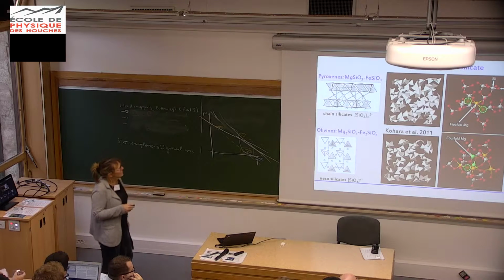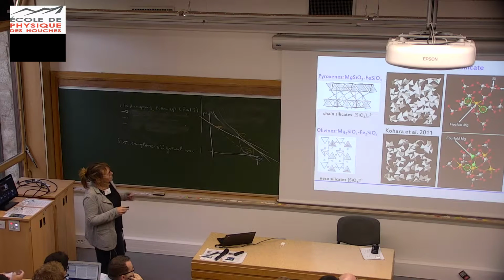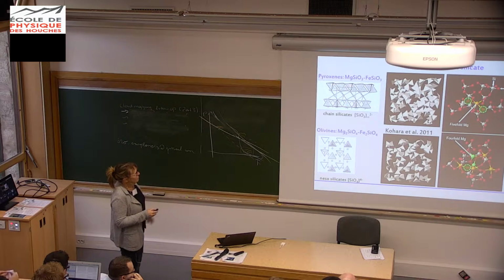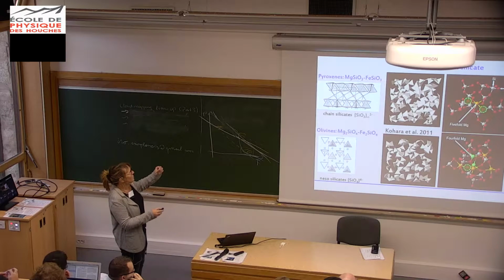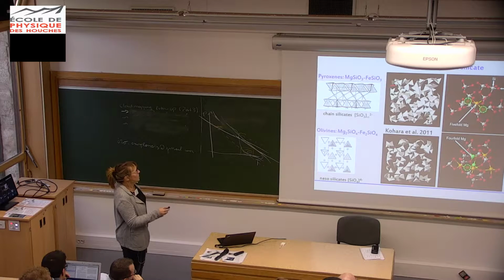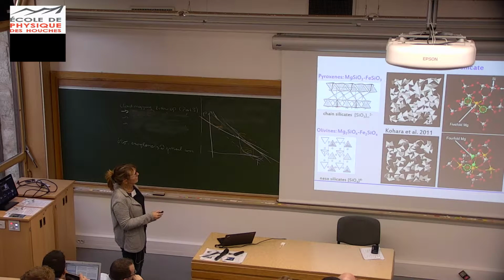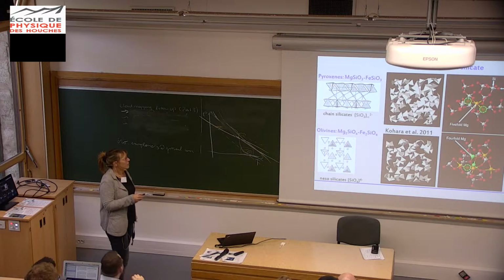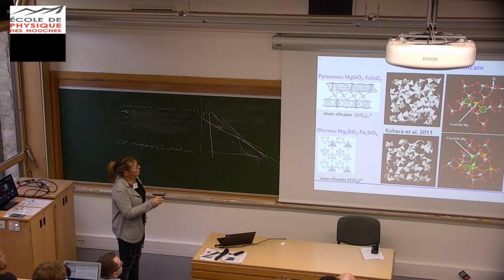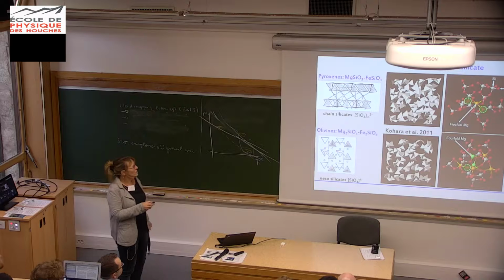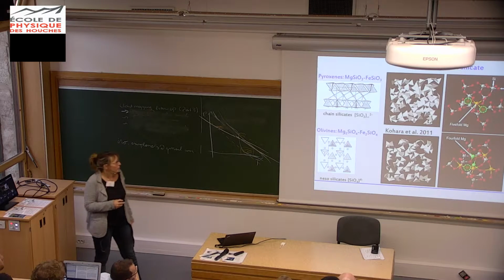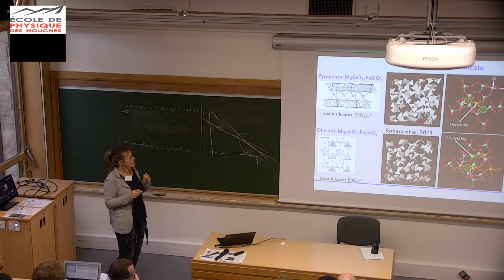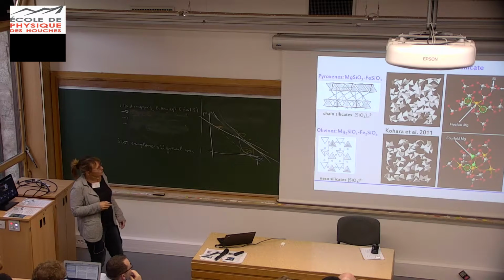Before I come to the results, a few words on the structures. Pyroxene and olivine are the crystalline materials. For the crystalline materials, we have a very definite structure. For the stoichiometry given here, we need chains of SiO4 tetrahedra, and in between these chains we have magnesium or iron cations. The pyroxenes form a solid solution series, so you can easily replace magnesium by iron, even though there are some slight changes in the oxygen-metal distances.